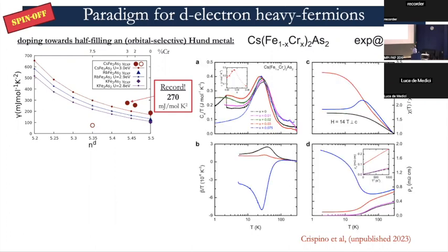And in fact, these are the experiments that were done on this cesium, iron, chromium, arsenic. And here you see the specific heat, which is indeed shooting up. The Curie to Pauli crossover, a nice T-square behavior of the resistivity. So really showing you that you have a heavy Fermi liquid in this state. And here you have magnetic susceptibility, thermal expansion.